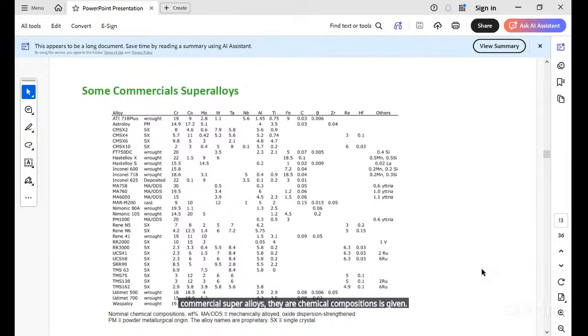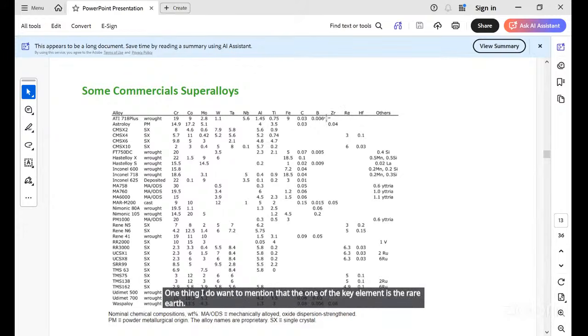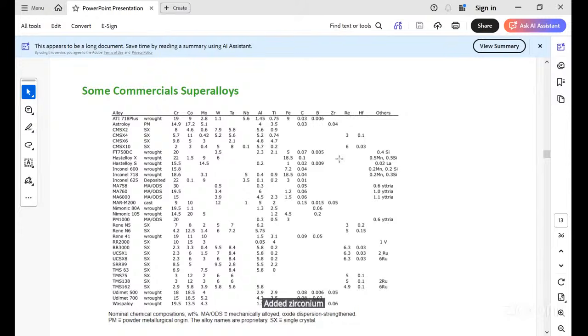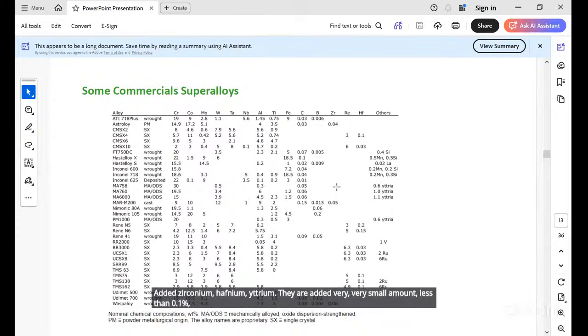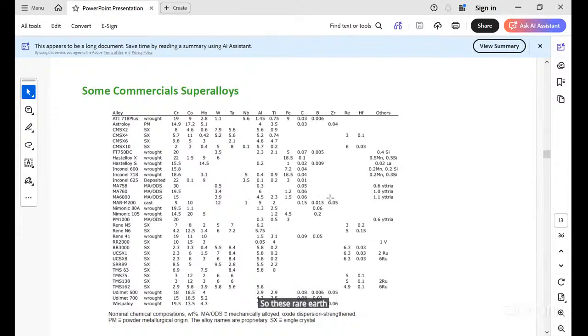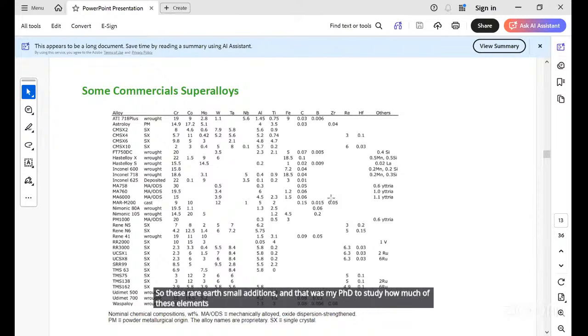One thing I do want to mention is that one of the key elements is the rare earth added: zirconium, hafnium, yttrium. They are added in very, very small amounts, less than 0.1%, but they increase the life of these components by 10 times or 100 times. So these rare earth small additions, and that was my PhD, to study how much of these elements and what do they do for increasing the life to 100 times by adding only 0.1% or even less sometimes.